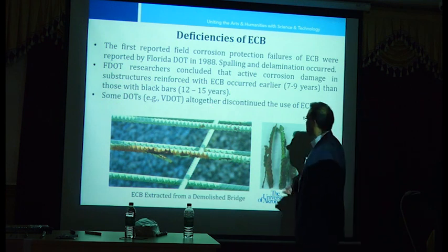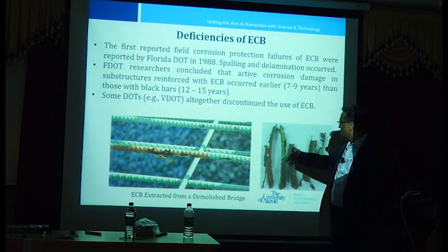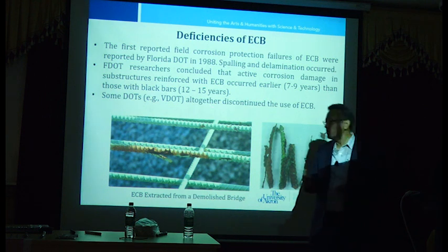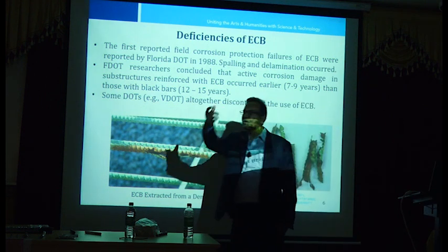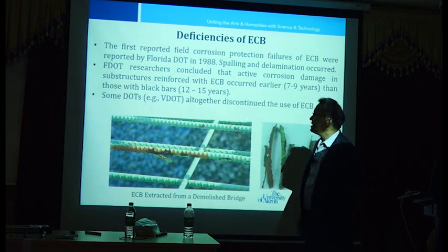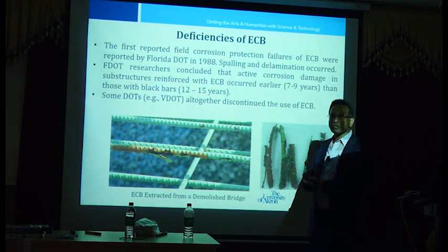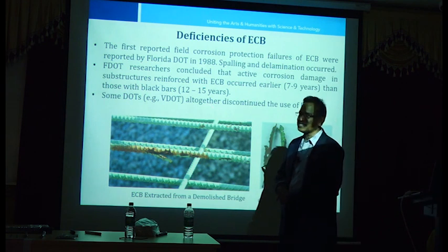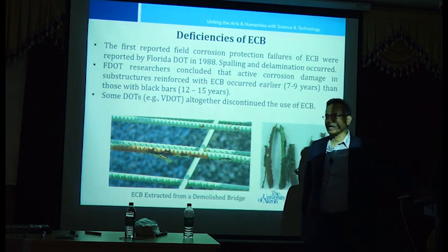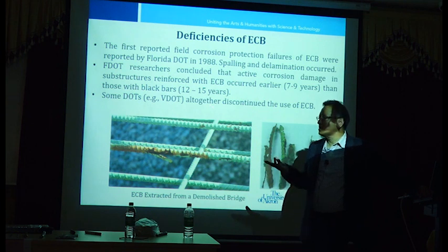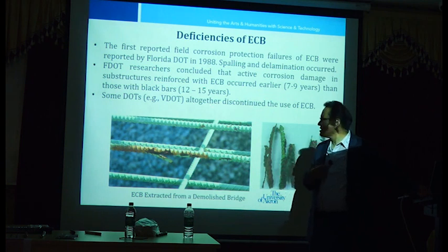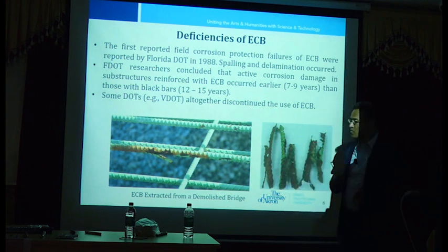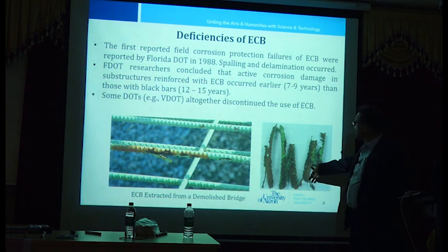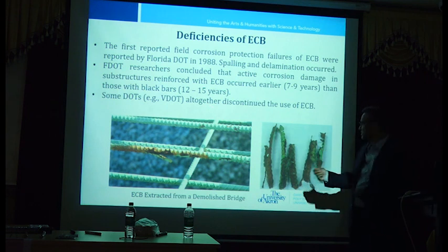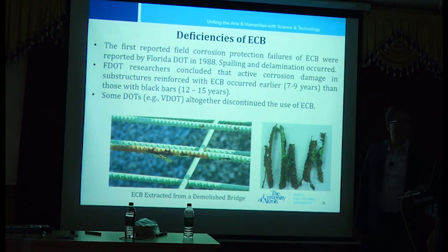So you can see how brittle these coatings become. They're very brittle. So it just peels off. You can, with your bare hand, just peel it off. So we think epoxy-coated bars are giving us protection, but it's really not giving the protection that we expect. So if somebody is trying to convince you that epoxy-coated bars are very good, they can be good, but we have a lot of issues with epoxy-coated bars. And you can just break it, it's very, very brittle material.